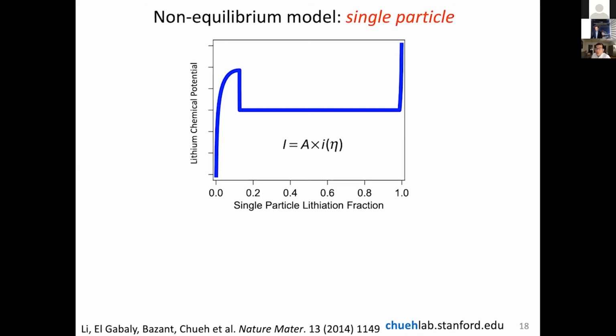Essentially, we are looking at the population effect, which means that if you take a standard single particle kinetics picture, it doesn't apply. You have to think of it as an ensemble of particles, which is the reality in most electrochemical systems. So let me show you what happens. For a single particle, if you just have one single crystal of lithium iron phosphate, this blue curve is your chemical potential. So this is basically the voltage of the particle as a function of the amount of lithium. So as you insert lithium, you are traversing this blue line. So this blue line is your open circuit voltage.